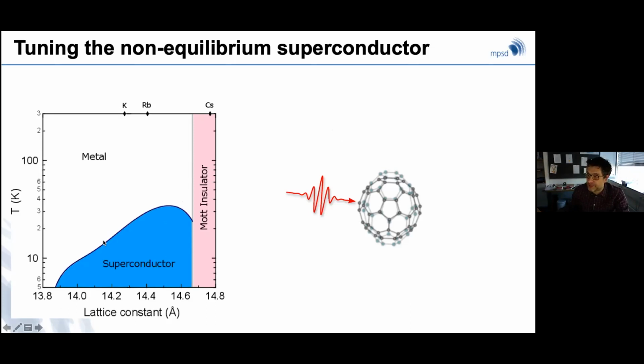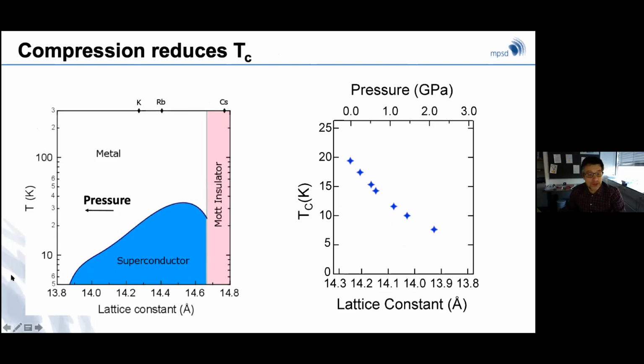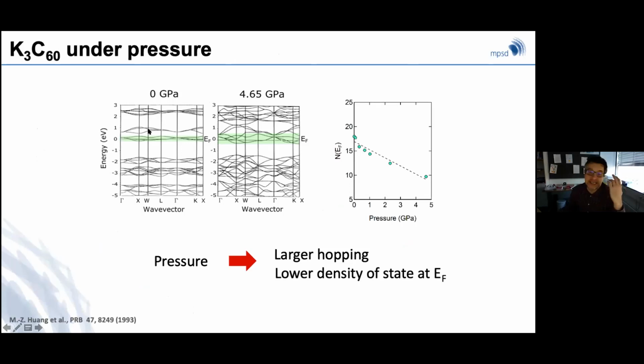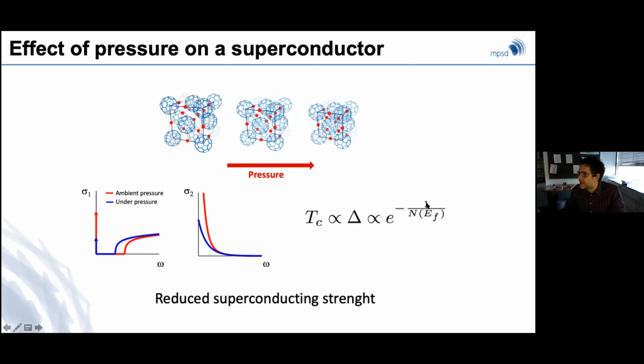Okay, so this is especially for potassium C60, which sits around here, 20 Kelvin. This is clearly applying pressure gives rise to a reduction in TC. So the reason for this is, at least in the context of very basic ideas of a BCS superconductor, that by applying pressure, the hopping amplitude becomes larger. So in a sense, the effective mass becomes smaller, and this reduces the density of states at the Fermi level, which by very simple concepts derived, for example, by the Macmillan formula, tell you that a superconductor will tend to become worse with pressure.